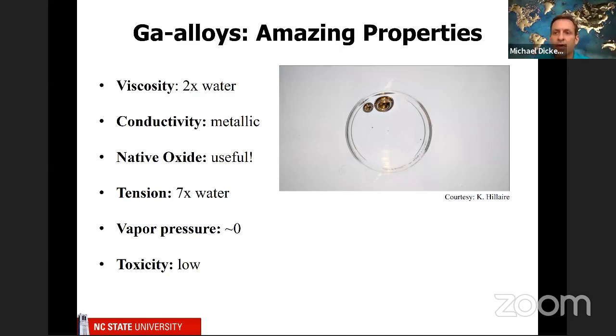Now, there's a couple of other things that are kind of interesting and remarkable. One is that it's got zero vapor pressure. So why is that important? Well, that means you don't need to worry about breathing it. It also means you can put it in a high vacuum chamber and it will not evaporate. That's very unusual for liquids. And then finally, a lot of times people say, oh, it's a liquid metal, it must be toxic. But I would argue that toxicity does not scale with melting point.